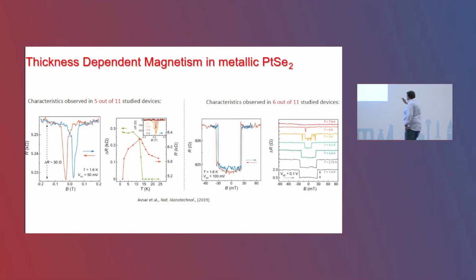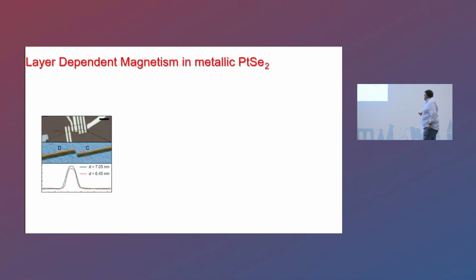And whenever we were focusing on the other devices, basically it was showing a zero-field antiferromagnetic ground state ordering. But whenever we were applying more field above the coercive field, the material was getting fully spin polarized. So it's kind of an antiferromagnetic type behavior. So what we were seeing is that nearly half of the devices that we studied were giving a ferromagnetic response, and half of them were giving an antiferromagnetic response.